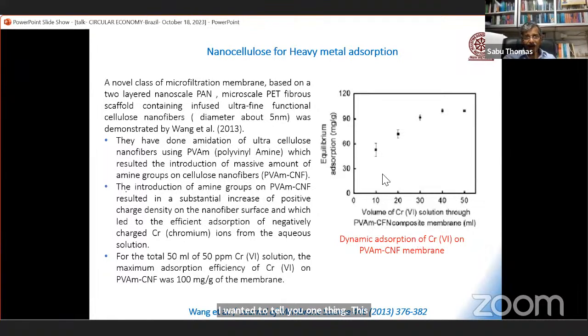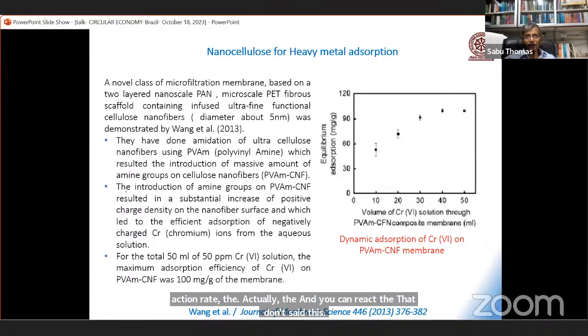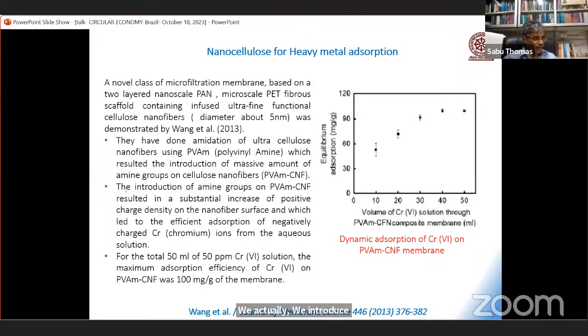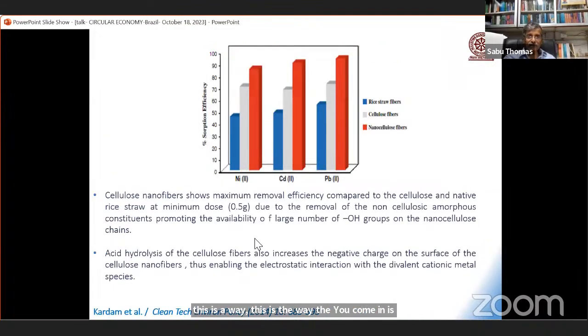So to accelerate the adsorption process, you can react the nanocellulose with polyvinylamine. You react with polyvinylamine, you can introduce massive amine groups on the surface of nanocellulose. So these amine groups are positive, and chromium 6 is negative. So you can have such interaction, and this is the way the chromium is removed. Similarly, you can remove nickel, you can remove cadmium, you can remove lead. So all these impurities could be removed. And some of them could be removed without any electrostatic interaction. Some of them could be removed by electrostatic interaction.